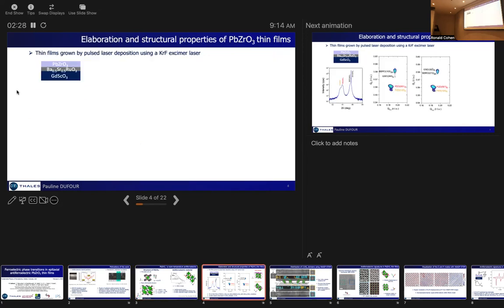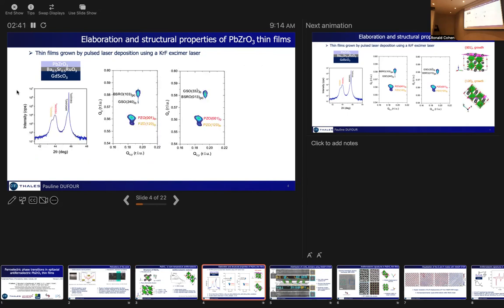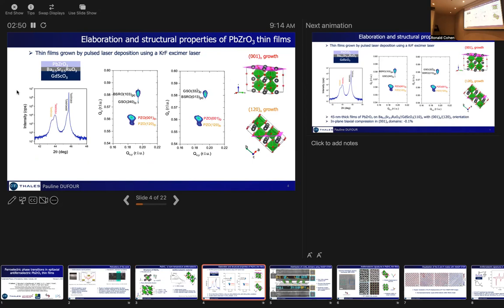So here we elaborated 40 nanometer thin films of lead zirconate by pulsed laser deposition on gadolinium scandate 110 substrate, and we used barium strontium ruthenate as a bottom electrode. The structural characterization through 2θ-omega scans and reciprocal space maps highlights that we actually have two different orientations in our thin films, the 001 orientation here and the 120 orientation, where in both cases, the pink plane represents the plane of our surface.